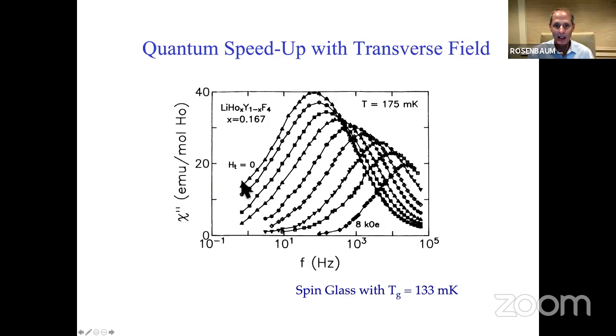And so you see here with 0 transverse field, a usual sort of response. This is actually for a spin glass system with a temperature about 30 millikelvin or 40 millikelvin above the spin glass transition temperature. You see a broad spectrum like this. It's about 3 orders of magnitude, almost 3 orders of magnitude, full width, half maximum. If this were a single spin, you would see 1.14 decades, the so-called Debye relaxation.